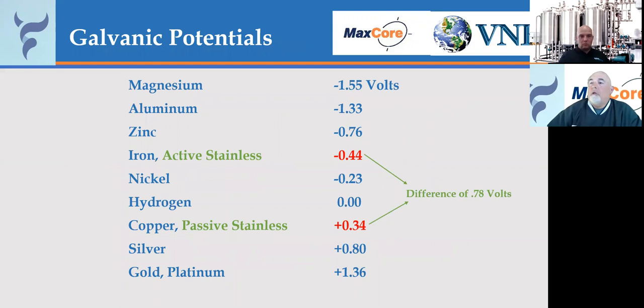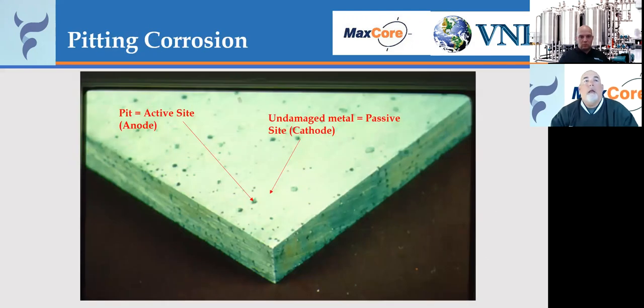And this is an example of what that might look like. So you can see here, this is a piece of steel that actually shows an active site of corrosion taking place at this particular area. This is your anode. You have a cathode, which is the undamaged passive steel. The metal itself is your metallic path. And then when this comes into play with the product, whether that be water, your product that you're pumping through, whatever that could possibly be, that's going to serve as your electrolyte. So you have that galvanic differential taking place on the surface of that steel. And whenever you have a pit start to form, it can really drill through material very, very quickly. And we're going to look at that here in just a second.